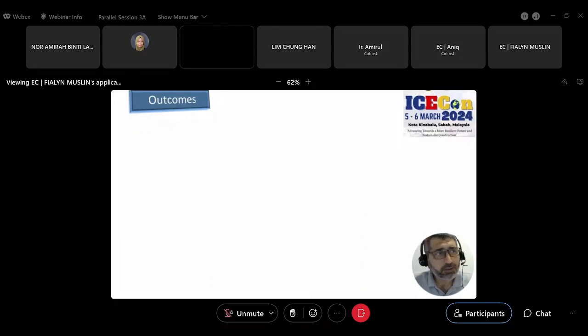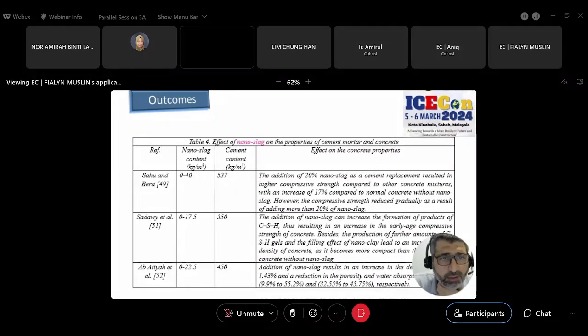Another table showing the outcomes here is the effect of nanoslag on the properties of cement, mortar, and concrete. Sahu and Bera used quantities of up to 40% nanoslag content, kilograms per cubic meter, with cement content of up to 537 kilograms per cubic meter. They showed that the addition of 20% nanoslag as a cement replacement resulted in higher compressive strength compared to other concrete mixtures, with an increase of up to 17% compared to the control specimen without nanoslag. However, the compressive strength reduced gradually as a result of adding more than 20%. So 20% was their optimum percentage.